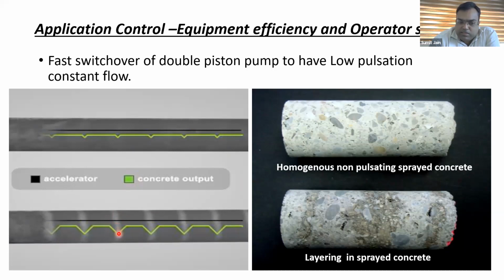So here you can very well imagine whatever concrete is going here has a very high accelerator dosage and it is going to burn. So these are the burning marks which you can see in black. These are the burning marks where the accelerator is actually more compared to the design dosage. And these marks give a very poor impact on the quality of the shotcrete. So we recommend to use equipment which is having a very low pulsation in the concrete flow. By low pulsation we mean the pistons are getting switched very quickly with each other. So when the pulsations are low, the layering effect goes away, literally. So we get a very good homogeneous sprayed concrete.